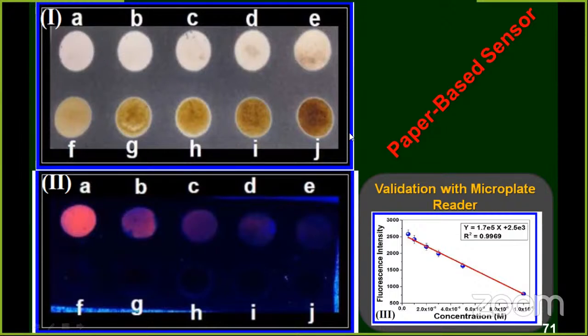After we prepare this, instead of ink, we have to fill it with wax. So that is a different printer, called a wax printer. Then we take a printout using our normal Whatman A4 size paper, then heat it on a hot plate at 180 degrees, and the wax melts. This is the wax area, and this is the wax-free area. The reason for using wax is that it is a hydrophobic area, and this is a hydrophilic area. We can hold the materials here because it is a liquid.